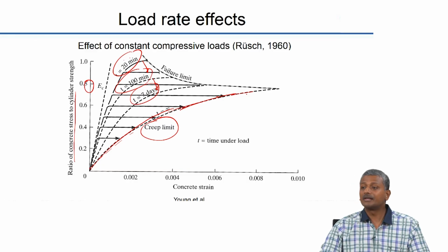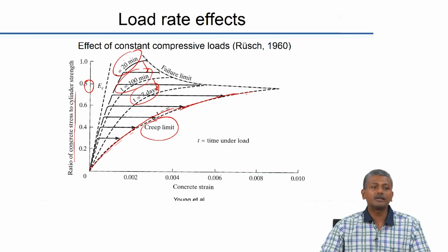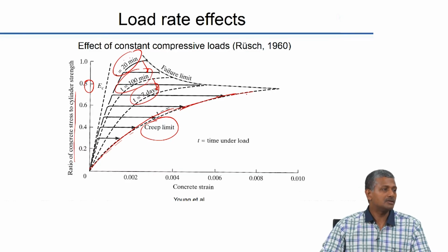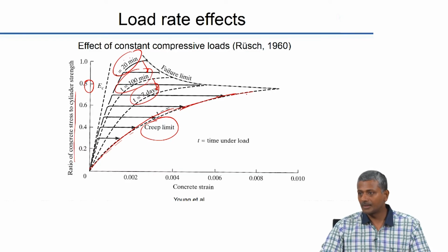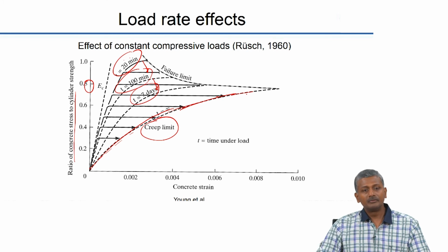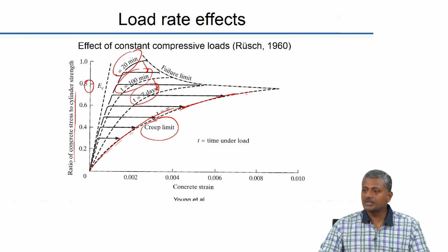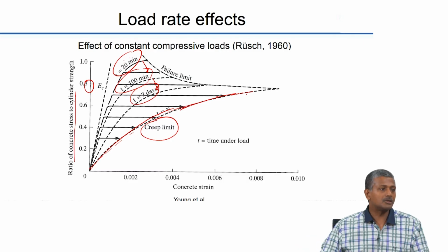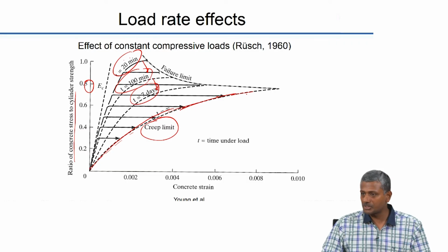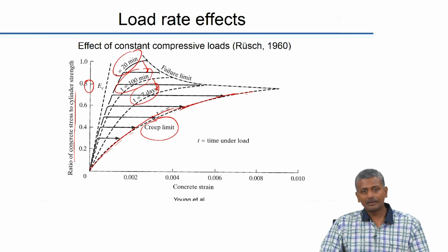So, for instantaneous loads or for sudden loading or impact loading, the strength that you get from your concrete is very high, but when you reduce the rate of loading by increasing the time that the loading is given to the specimen, the strength that you get from the specimen is lower. So, that is why when you do the compression test or a tension test on concrete, you need to very clearly specify the rate of loading.